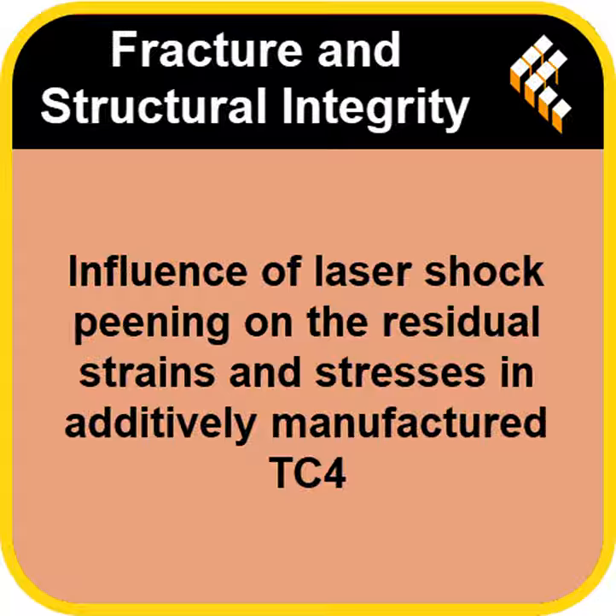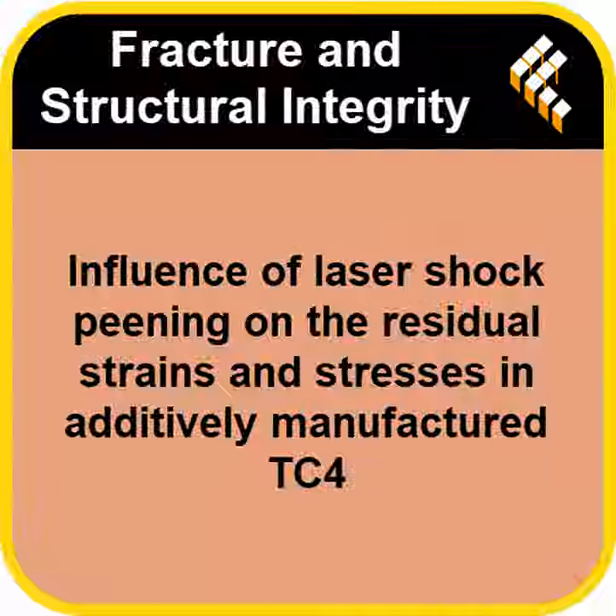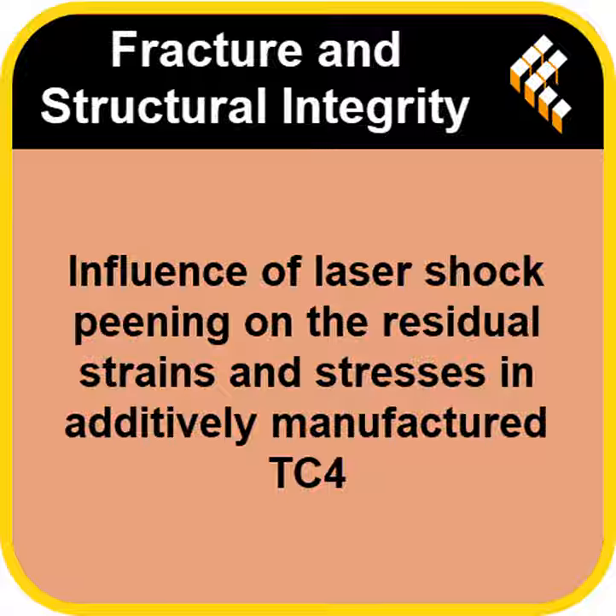But did the LSP work? Did it convert those stresses? It did, thankfully. After LSP, they consistently measured those beneficial compressive stresses, and they went quite deep. How deep? They observed the effect down to at least 1 millimeter below the surface. That's pretty significant penetration for LSP.